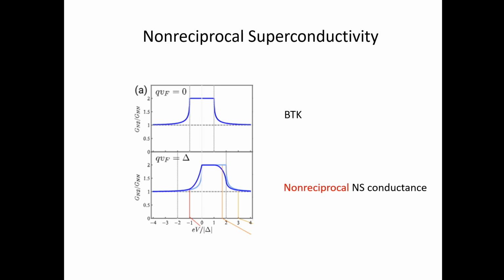And for conventional superconductors, the famous BTK formula tells us that the conductance inside the superconducting gap will be enhanced, reaching twice the normal conductance. However, for a non-reciprocal superconductor, and one way to achieve this is to think about a superconductor with finite momentum, you can see that this doubling in conductance now occurs at a finite bias voltage. It centers around a region at a finite bias voltage. So in this case, the IV curve is clearly asymmetric. So in other words, this NS junction can be a good way to probe the intrinsic non-reciprocal properties of the superconductor.